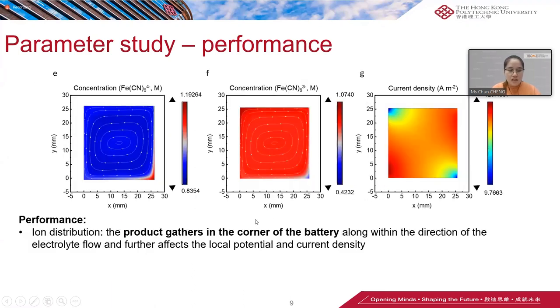So figures E and F profile the ion distribution in the electrolyte. Since the flow velocity of the electrolyte at the corner is almost zero, the products gather in the corner of the battery in the direction of the electrolyte flow and further affect the local potential and current density. So you can see that the current density of the corner is much lower than the other places.